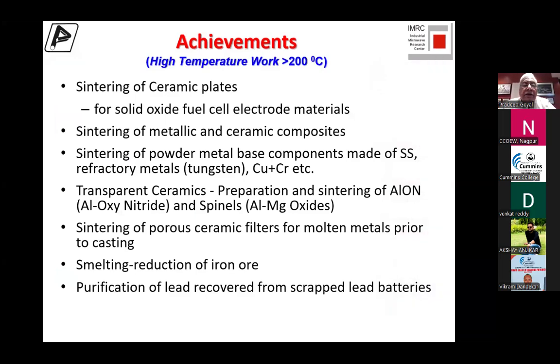Initial trials were conducted with a lot of different high temperature works. We did sintering of ceramic plates for solid oxide fuel cell, electrode materials, metallic and ceramic composites, sintering of powder metal base components made of stainless steel, transparent ceramics. So all of these are things that we made a lot of experimentation, but we realized sooner or later that many of these may not convert into commercially viable processes. It was a great learning experience for us, but we did do a lot of different kinds of products that we tried to process in these furnaces.